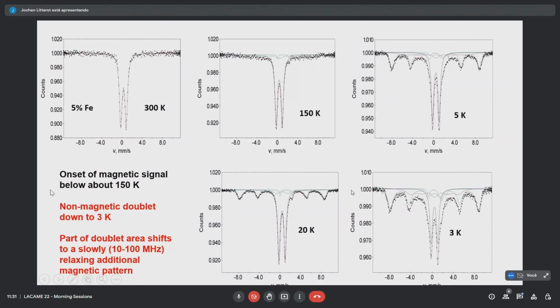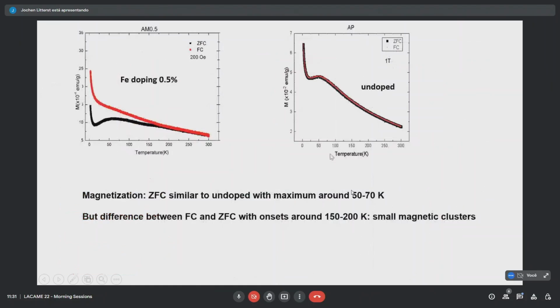Now, how does the Mössbauer spectra look? That's actually not done with 0.5%, it's done with 5% of iron. With 0.5%, we should have worked with enriched iron, and that was done with unenriched. You see nice doublet patterns at high temperature. Going to low temperature, you see some onset of some magnetic background. That's where we also see the onset of correlations in magnetization. At lower temperatures, that develops to clear sextets which are horribly broadened.